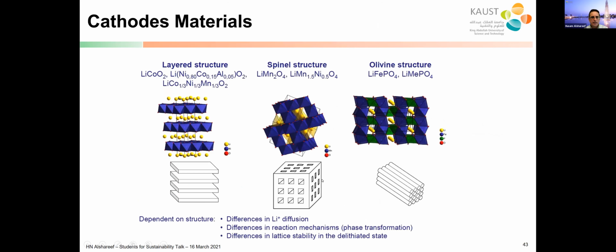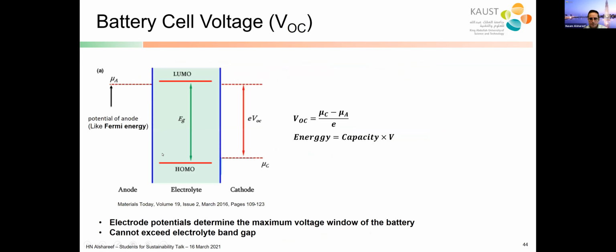On the cathode side, we have oxides mostly, and we are dealing with oxides that have either tunnels like this one for the lithium to go in and out, so we have planar 2D tunnels. We have these 1D tunnels, and we have these 3D tunnels. So the prerequisite for these oxides is to have really an open structure and to be structurally stable, to welcome the lithium and let it diffuse in and out fast. And people now with simulations can actually predict structures, predict absorption energy of lithium on different structures, and predict or guess what replacement materials may be used.